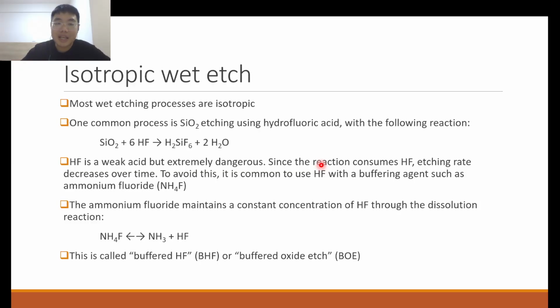Okay. So what happens in this etch is that a chemical reaction occurs, and when a chemical reaction occurs, your reagents are consumed. HF is being consumed, so the etching rate actually decreases over time because the concentration of HF decreases. So what they normally do is use HF with a buffering agent such as NH4F. If you remember the idea of a pH buffer, it maintains a constant concentration of hydrogen ions because of the dissociation equilibrium. As one side is being consumed, the equilibrium position will shift to offset the change. So as HF is being consumed, the equilibrium of NH4F producing NH3 and HF will shift to the right to produce more HF to compensate for the consumption of HF in the etch reaction. This is called buffered HF or buffered oxide etch, BOE. It's quite a common term.